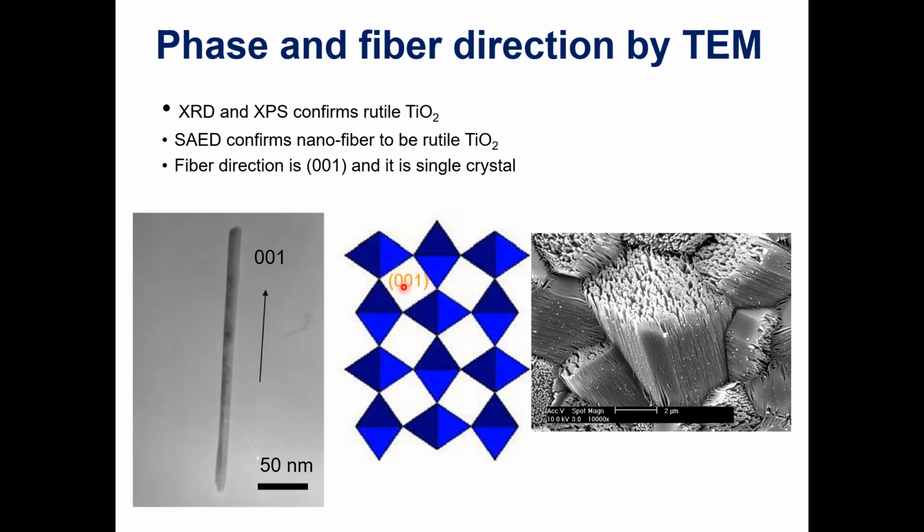Initially we thought that there was diffusion anisotropy along that direction, but looking at the data, the diffusion anisotropy in that direction is not very different from the other direction. On the other hand, on the 001 surface, there is strong reaction anisotropy, and I'll talk about that. You can see that these are single grains, and this is some initial stage of etching, where preferentially the 001 face is being etched.